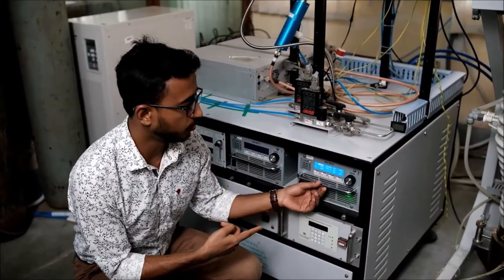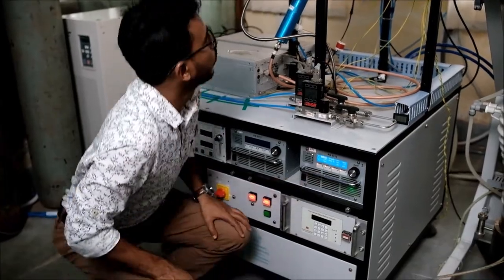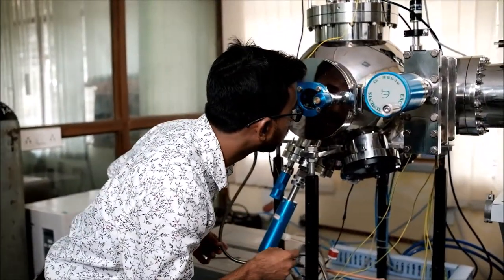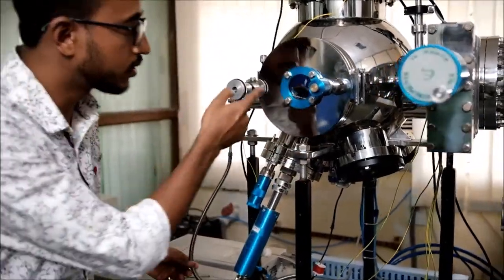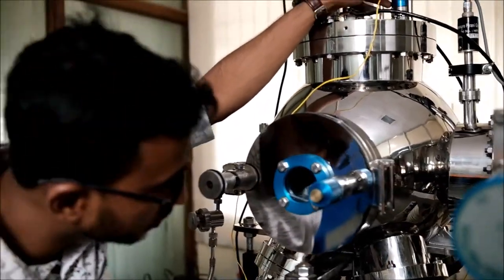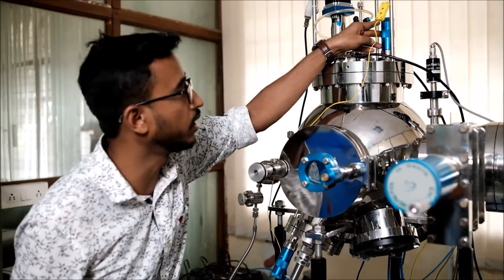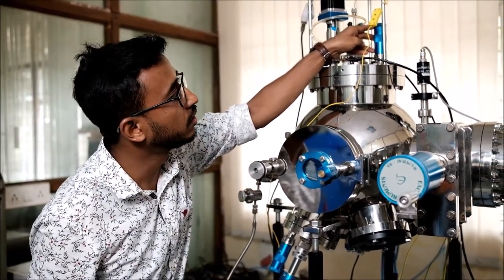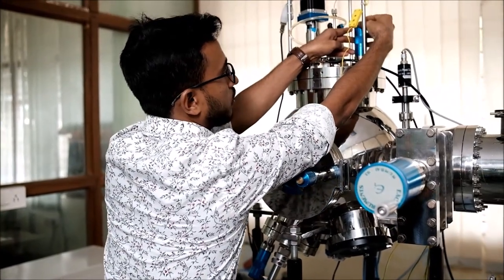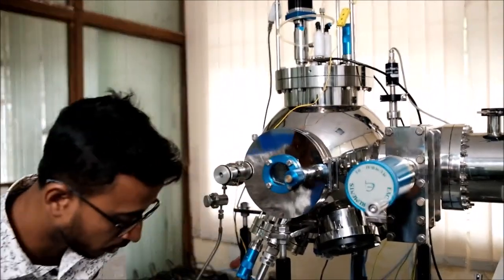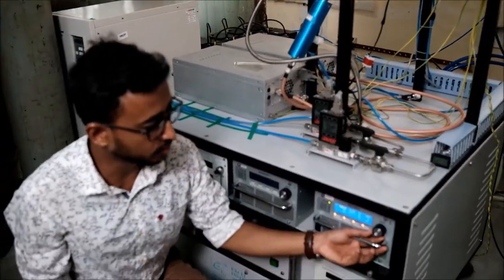Now I have reached a power of 30 watt, and I can already see the plasma has already striking. So you can see the plasma. You can consider this sputtering as a pre-sputtering process, and we do this pre-sputtering before the actual deposition all the time. And you see, we have covered the substrate with this shutter, and when we want the actual deposition, then we open this shutter. We will continue to increase the power till 50 watt.